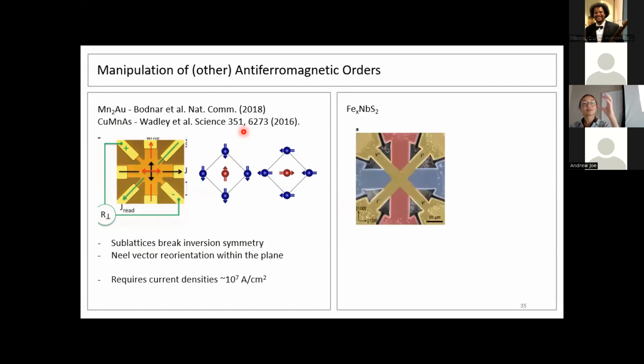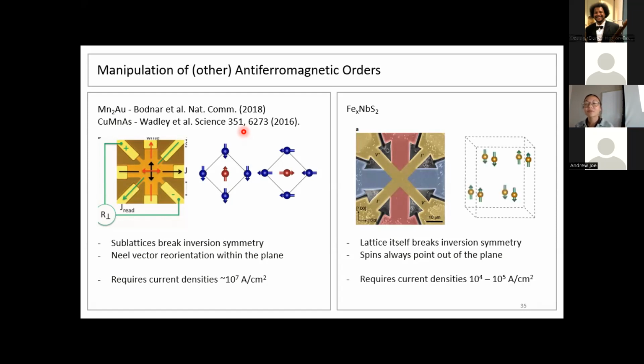Now in our system, again, very similar device, our symmetry considerations are slightly different, although this should in principle still be possible just through a slightly different channel. But we've learned since doing these initial measurements, through some other measurements, that our spins are actually always pointing out of the plane. They're always pointing either up or down, so there's no room for there to be a 90-degree reorientation, because they would never point 90 degrees away from the axis that they like. And I'll add as well that we require much lower current densities, although that's kind of a flex.